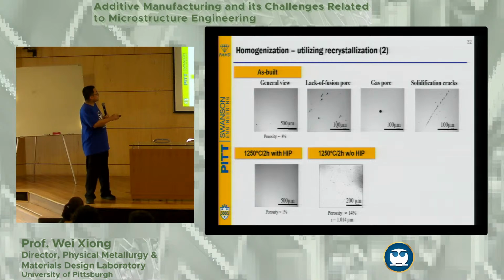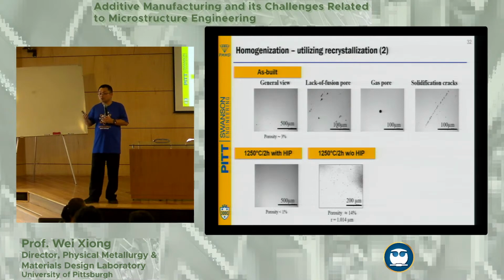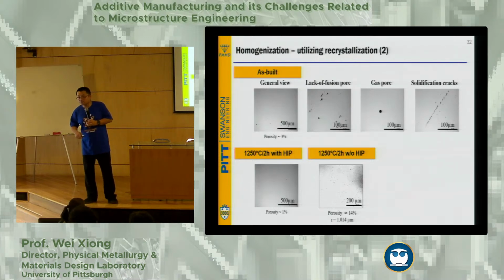Because you have this very small submicron features still there, and then they can grow. But then with these gas pores and spherical shaped pores, after the HIP process, it's a little bit better, so they will not reconnect with each other. So that's kind of the idea.